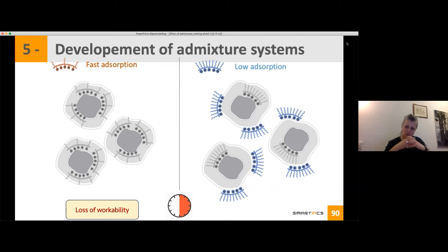In the other case, I also have some hydration phase that grow on the surface of my cement. But in that case, what I have still in solution, I still have PCE, it is there. And then you say, okay, maybe that PCE has more affinity to adsorb on your ettringite than to adsorb on your C3A. So when you have your hydration layer that grows, then you still have next to the hydration part, you still have some PCEs that can adsorb. And because it's adsorbed on the surface of the hydration layer, then you still create dispersion. So in that case, you have increase of the functionality of your PCE, and it's how you create water retention.